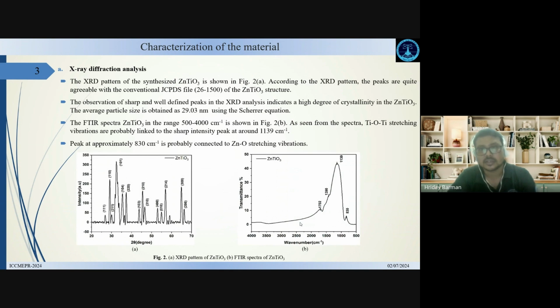Firstly, the XRD analysis. As we can see in figure 2A, according to the XRD pattern, the peaks are quite agreeable with the conventional JCPDS file, and the sharp and well-defined peaks in XRD analysis indicate a high degree of crystallinity in the zinc titanate material. We have also calculated the particle size using the Scherrer equation. It's about 29.03 nanometer. We have also done the FTIR spectra of zinc titanate between 500 to 4000 per centimeter, as shown in figure 2B.